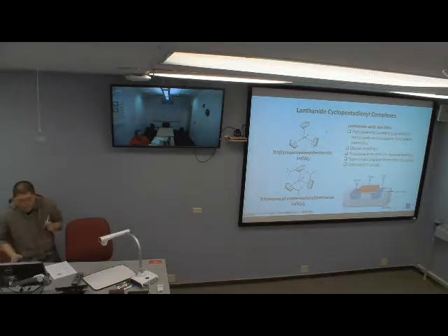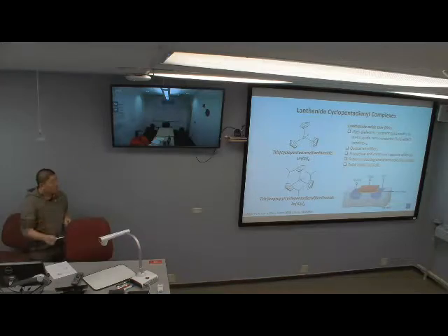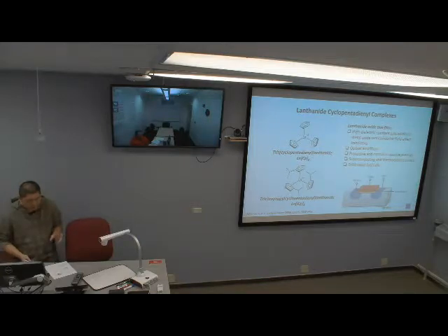And the lanthanide oxide thin film has many applications. One problem of using lanthanide cyclopentadienyl complexes to prepare lanthanide oxide thin film is carbon contamination. So by studying the photofragmentation of this compound, we can determine the contamination source, and we can even control the contamination.